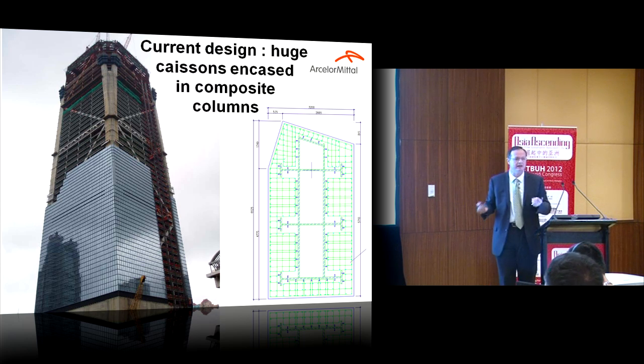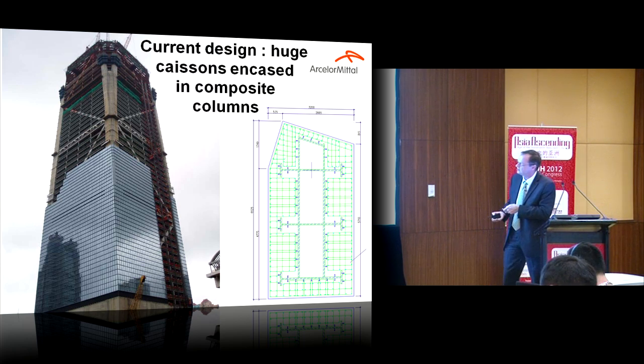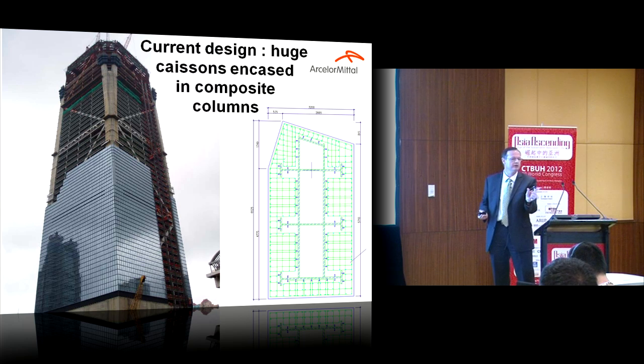If you follow the welding codes, here in this case they are using 65 millimeters and 50 millimeters plates. According to the welding codes, you must preheat the whole section at 110 degrees centigrade before and during the welding.